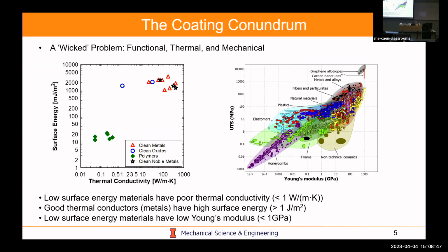So for example, if you look at material surface energy for things like clean metals, oxides, polymers, and noble metals, typically the materials that have higher durability, like metals and metal oxides, have high surface energy, which is what you don't want. You want low surface energy. Then if you look at thermal conductivity, metals have high thermal conductivity, which is what you want for many thermal applications, but they also have high surface energy. And so in reality, the materials you're left with here are polymers. And polymers have very poor mechanical properties.